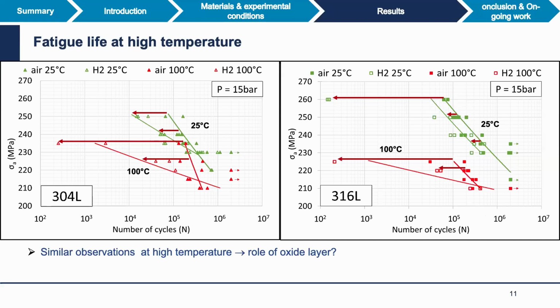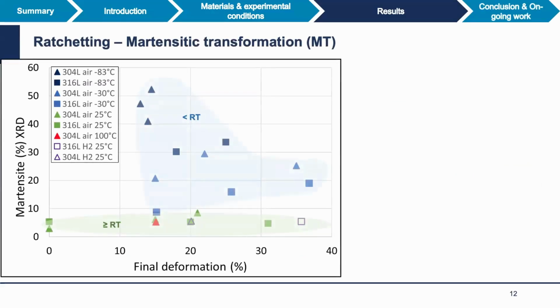So one explanation could be that we have a barrier for the hydrogen ingress at low stress amplitude due to the presence of the oxide layer, and that we would need to stress the material to a high level in order to break this oxide layer. But you have to keep in mind that you also have this high deformation. And generally, we also think about the martensitic transformation to account for the loss of performance at low temperature.